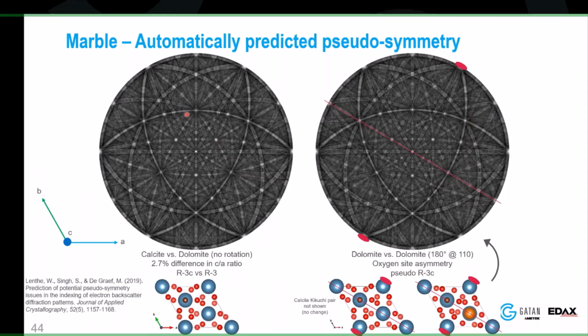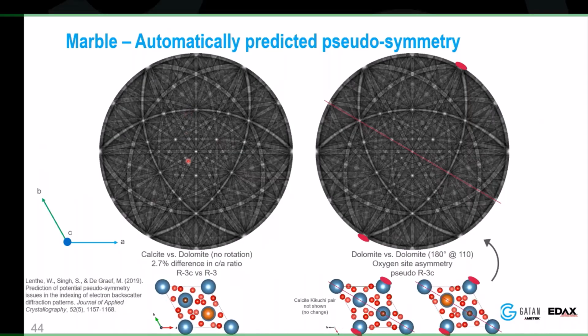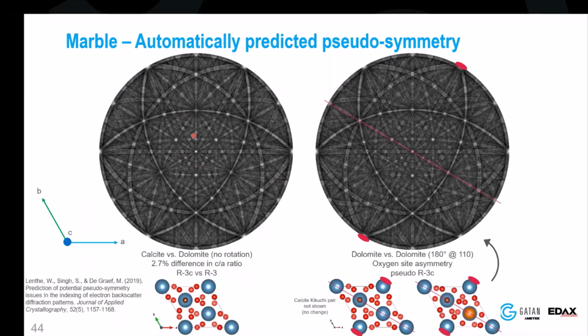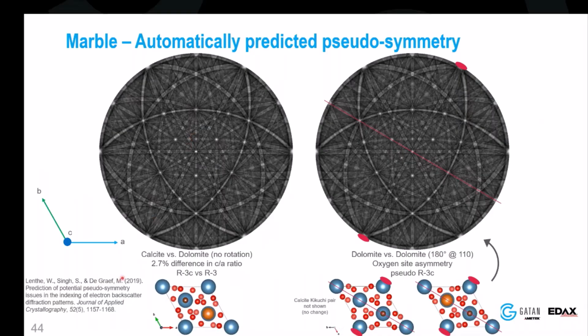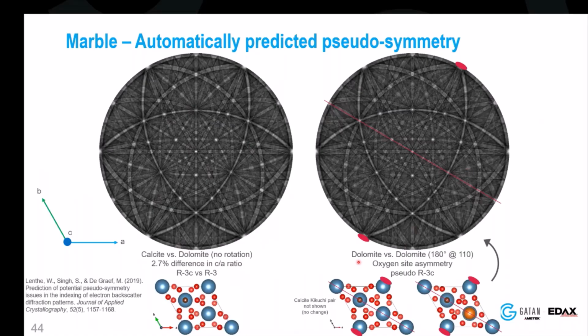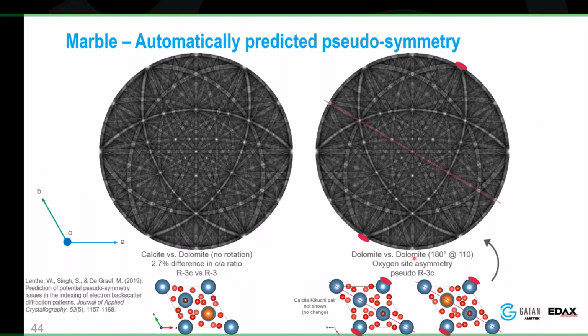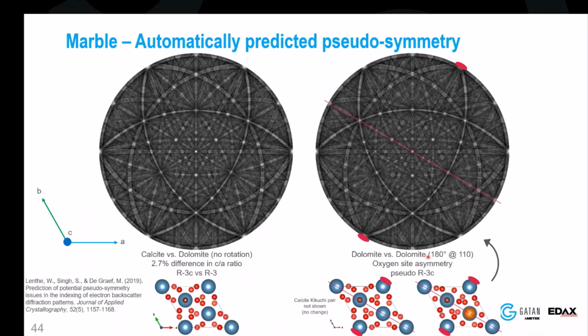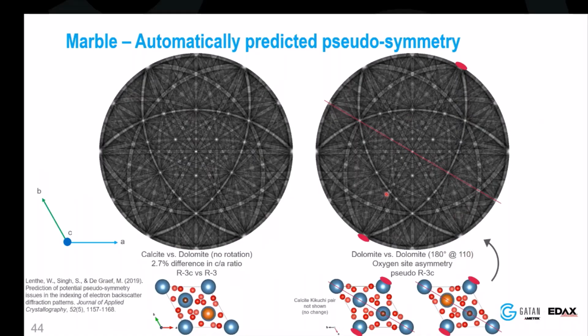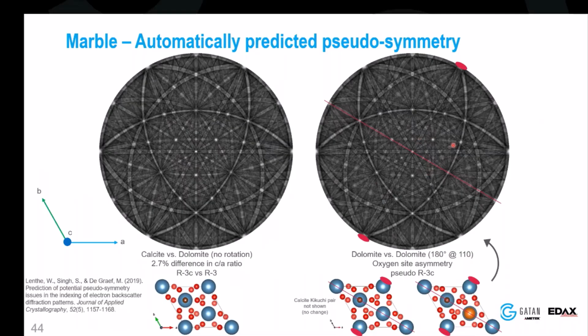Now, depending on the orientation you have, this can be a very difficult problem for the Hough-based transform, because again, in certain orientations, the amount of differences here is going to be pretty small. And again, this is what we call a pseudosymmetry problem. Over here on the right-hand side is actually dolomite versus dolomite. So again, certain orientations of dolomite, in this case, rotated 180 degrees around the 110. You can see that again, there's not that much difference between these two patterns. So again, the Hough is going to have problems with this dolomite pseudosymmetry problem over here, because there's not much difference.